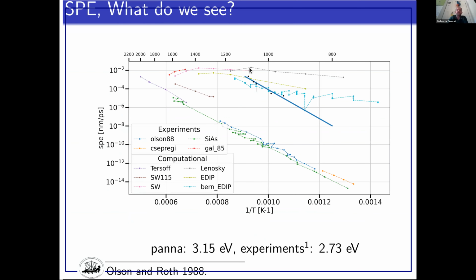We are estimating the magnitude of the recrystallization speed, and our estimated activation energy is 3.15, and the experiment is 2.73 electron volt. So they are compatible, so they are reasonably in good agreement.